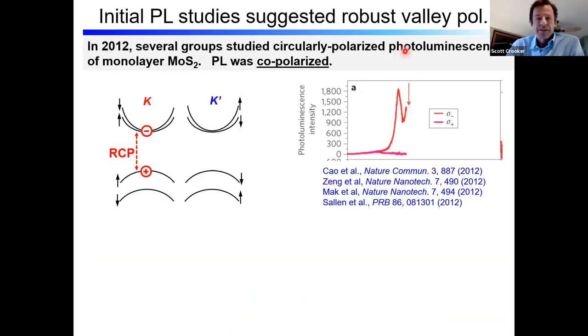Okay. And in the early days of this field, it was not so long ago, several groups were studying just the photoluminescence from these, and the initial study suggested a very robust valley polarization, meaning that they pumped the system with right circularly polarized light, and then most of the photoluminescence that came off was also right circularly polarized. And this got everybody all excited. A robust valley degree of freedom. We're going to use this as qubits as a basis for quantum computation, blah, blah, blah.